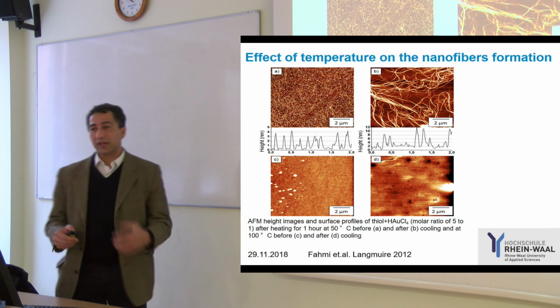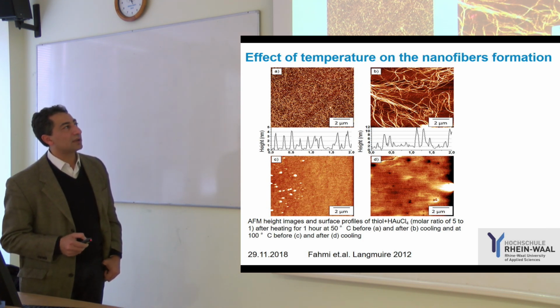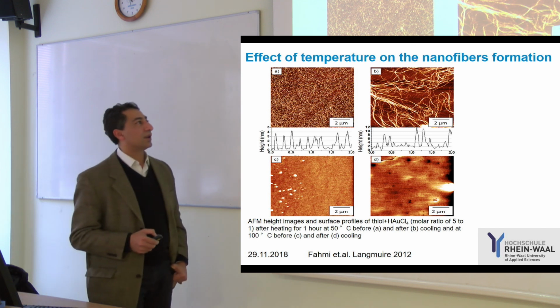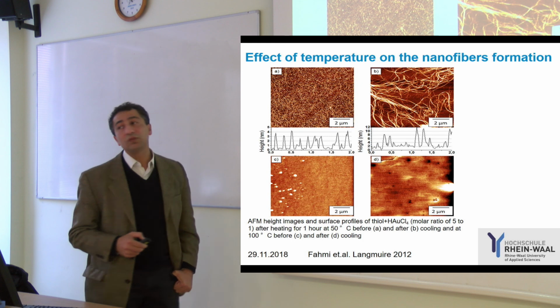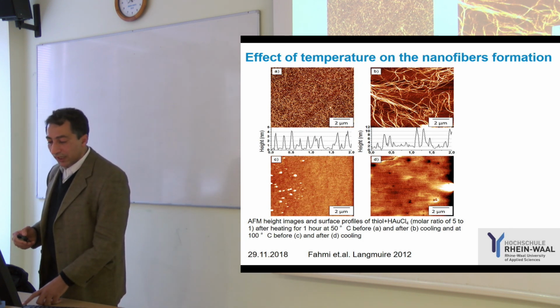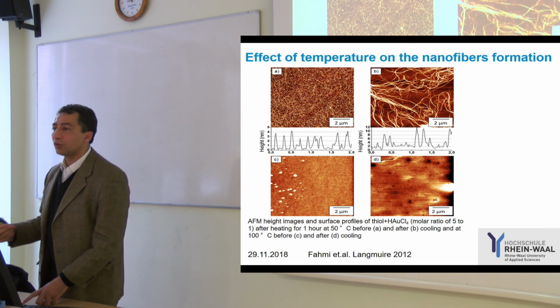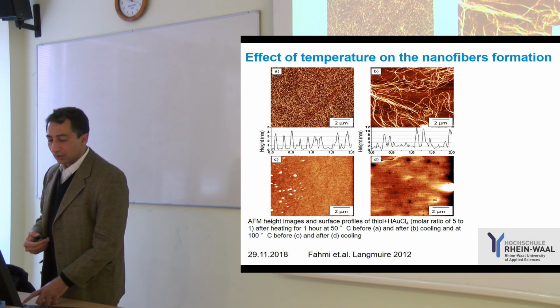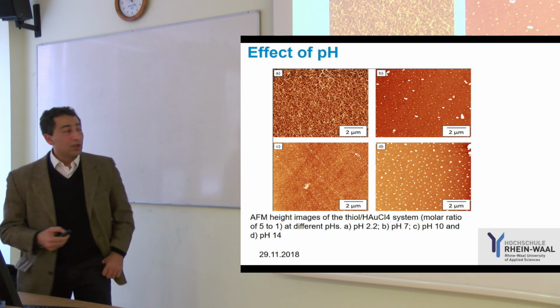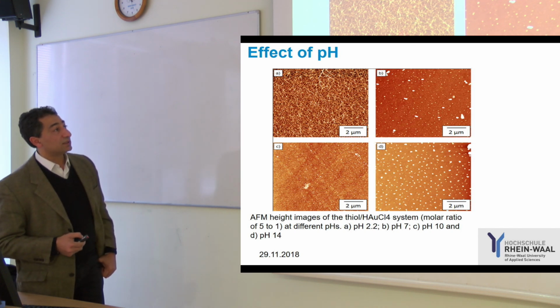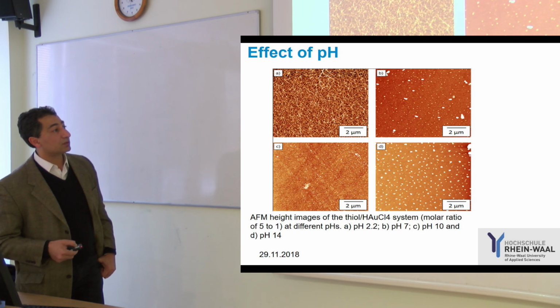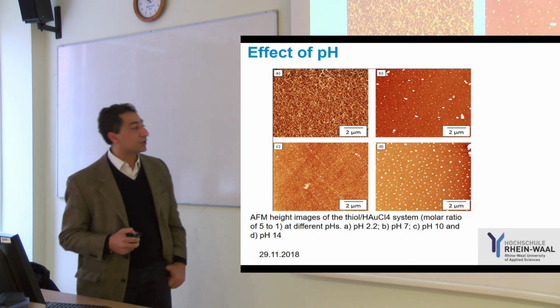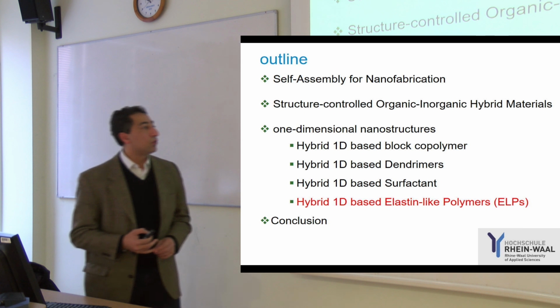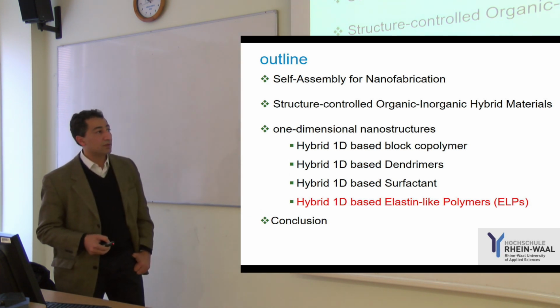If you have such a structure built on hydrogen bonds, we have to work more on how the structure looks. We look at temperature, how it influences the different levels of structure, and you can have different thickness. You can prove the dominant driving force here. It is more likely the hydrogen bonds, which you can influence just by temperature, so that you can assemble and disassemble the structure in different ways. We study not only temperature, we study the pH. We can see we can disassemble the structure from fiber into particles, into different sizes of particles, simply by changing the pH. That was the third story about surfactants. By this we moved from polymer dendrimers to very short surfactants.